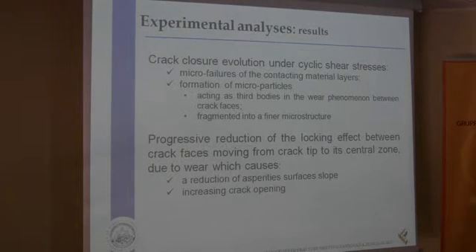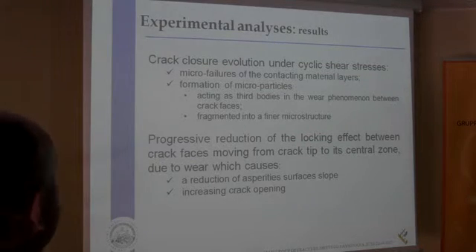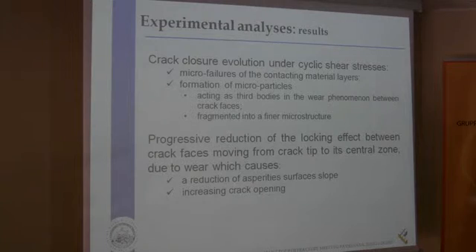So, to summarize the experimental evidence, we can make some comments on the crack closure phenomenon and its evolution under cyclic shear stresses. We saw microfailures of the contacting material layers and consequent formation of microparticles, which act as third bodies in the wear phenomenon between crack faces, and sometimes are fragmented into a finer microstructure. As a consequence, we noted a progressive reduction of the locking effect between crack faces, moving from the crack tip to its central zone, due to wear, which causes a reduction of asperity surface slope and increasing crack opening.